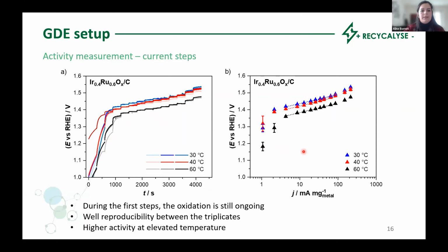And in the B graph, the so-called Tafel plot is represented. This means that the log scale of the applied current is plotted against the potential. We are expecting to observe a linear behavior if only kinetic processes are happening, and we see that it is the case where the catalyst reaches the steady state behavior. Furthermore, on both graphs, we see that at higher temperature, the catalyst becomes more active, and this is expected from kinetics.